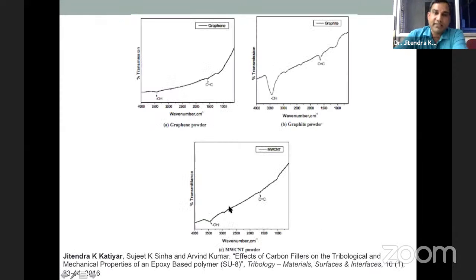So this FTIR I performed on 3 carbon materials, and this paper was my first paper in my PhD, and it was published in Tribology Materials Surfaces & Interfaces. So in this paper, I chose 3 carbon materials, and I wanted to analyze which is the best carbon material amongst all, graphene, graphite, and MWCNT, which gives you the lowest friction coefficient, and why. So in this, I tested graphene, graphite, and MWCNT.